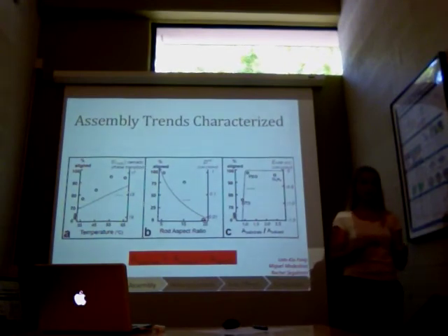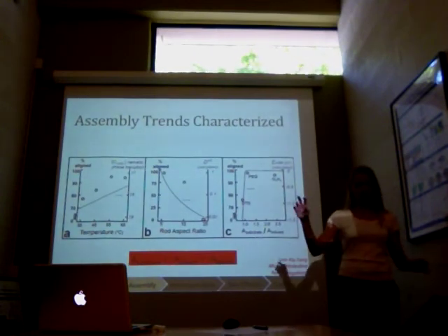And then the aspect ratio, are longer rods better typically, or shorter rods better? Your film is proper thickness? So longer rods are certainly better for making the film thicker, and we used the longest rod that we were able to reliably get to stand up. And so those were somewhere between 30 and 40 nanometers long. As we got to longer rods, we weren't able to find a set of conditions that allowed them to kinetically reach the place they needed to get.